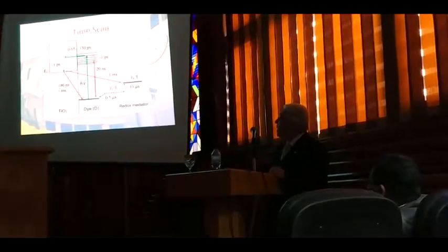But there is a competing reaction, where the excited electron returns back to the ground state and there is no electricity, or it goes to the conduction band, but from there it returns back to the ground state, and then you don't have any electricity. So you want to adjust the conditions to make the first reaction the more efficient.